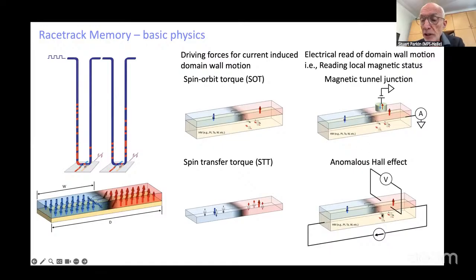Alternatively, we could use something called the anomalous Hall effect. It's not a spin Hall effect, but an anomalous Hall effect, which is within the magnetic layer itself, where a charge current, through spin-dependent scattering, has electrons with spin up and spin down scattered with different probabilities to the left and to the right. This leads to a transverse voltage like a Hall voltage, but the Hall voltage here is spin polarized. And this spin polarized Hall voltage can be used to detect the magnetization, whether pointing up or down. The sign of this anomalous Hall voltage will change when the magnetization is switched from up to down.